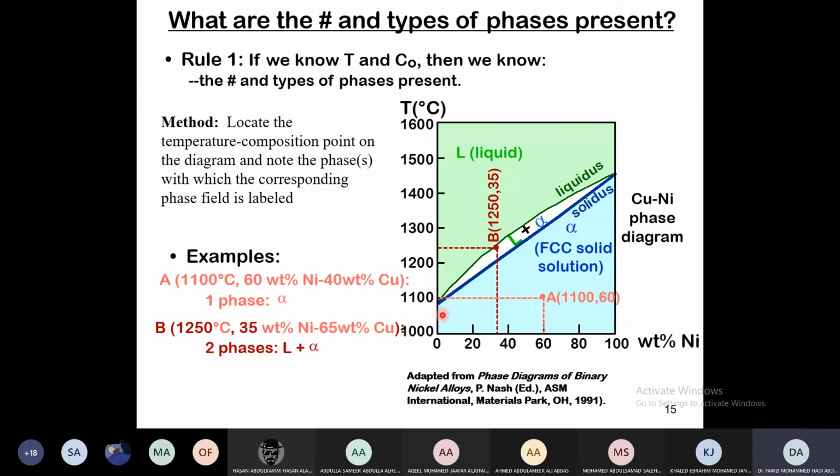It's called direct melting. It's called simple melting, or simple solidification, if you want, if you're coming back, if you're cooling, for example. So this happens for pure metals across a point. The same thing here: the nickel, pure nickel, the melting happens across a point. While for an alloy with different compositions here, it does not happen across a point. It happens across a range of temperature, as we have explained last time.